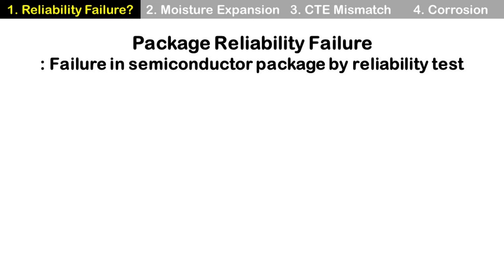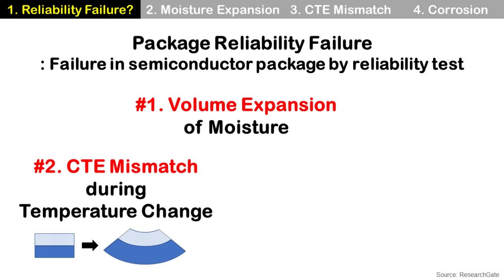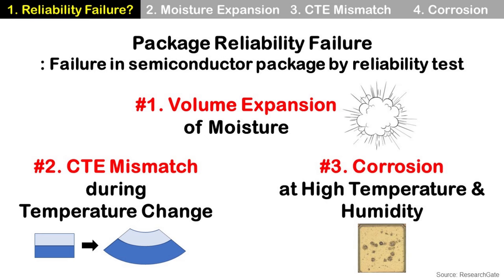Package reliability failures means failures in semiconductor packages during reliability testing. There are three major causes: first, volume expansion of moisture; second, CTE mismatch during temperature change; and third, corrosion at high temperature and humidity.